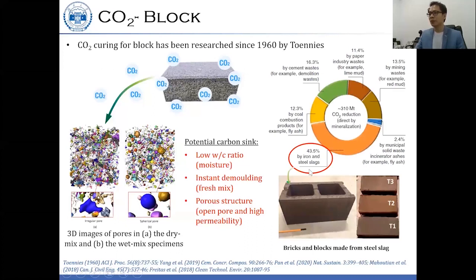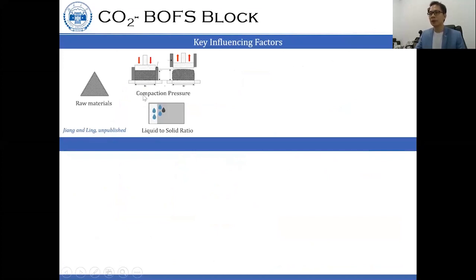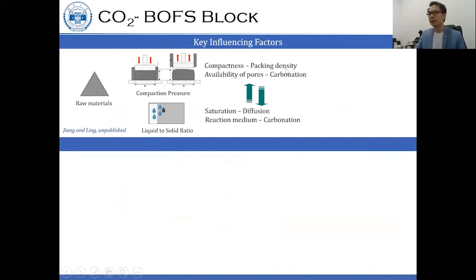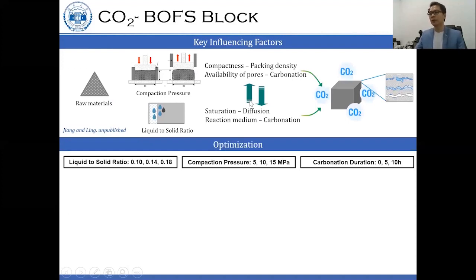And we also can incorporate different kinds of CO2 active material, for instance, steel slag as the binder to make the concrete block with a very high strength. And we know that, apart from the raw material, the key influence parameter affecting the performance of concrete block is the compaction or molding pressure or the liquid to solid ratio, because the compaction will influence the packing density and availability of the pore for carbonation. So the liquid saturation also influences the diffusion of the CO2 for the carbonation. So in our study, we have studied the different parameters: liquid to solid ratio, the molding pressure, and also the carbonation duration.